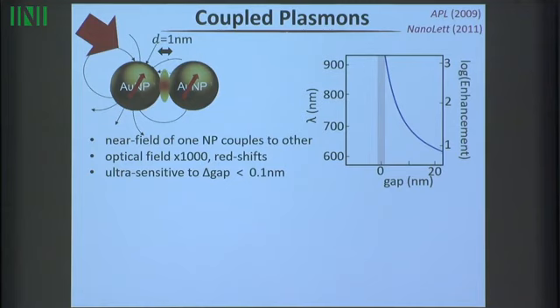So this is fearsomely distance dependent. So we became more and more interested in actually controlling these gaps on the scale of a nanometer. What happens is there's a particular color that gets trapped in that gap, and the smaller the gap, the redder that is. And it's like a capacitor. The energy of the system drops, becomes a redder system as you confine it more tightly.